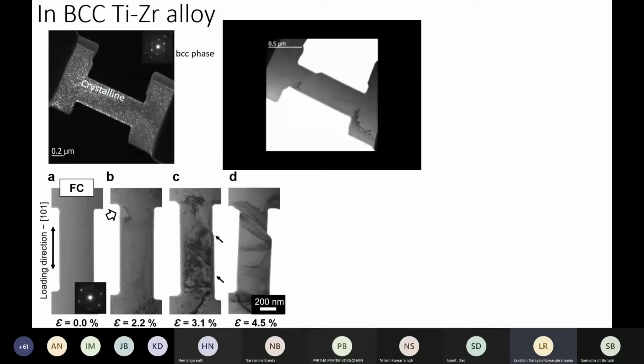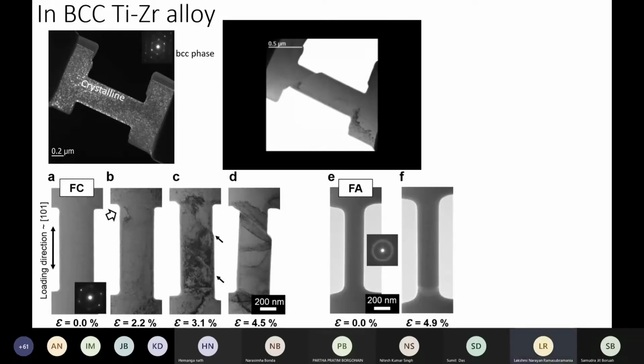So if you look at the sequence of events, at 0% strain, you don't see much. As you increase the strain, certain features start developing in the crystal, and you see there are two slip bands which are activated. These are snapshots taken from the same TEM video. And you see that the material has undergone shear over one plane, and after that, the other plane which was activated initially at 3.1% stops getting slipped. And failure has already occurred.